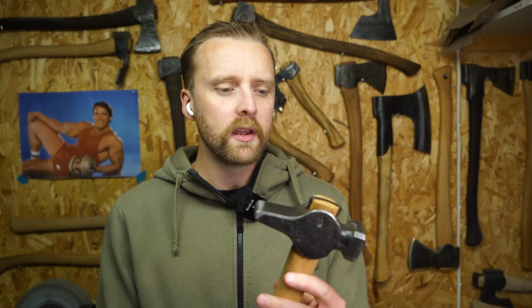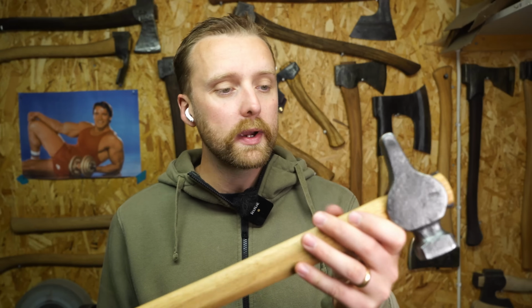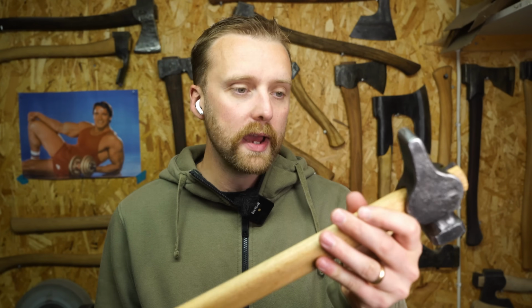I was also quite impressed actually how well the spring fullers worked and how much material you can move under them. Now I did use a heavy hammer, I did use my 2.5 kilo hammer. That helped a lot. Now starting with a smaller stock billet also means that the hammer itself is lighter than my other hammer, but it's still heavy enough for it to be a very comfortable weight when forging. So this hammer weighs all in all 900 grams, so almost a kilo, which is a very comfortable weight in my opinion to use as a forging hammer.